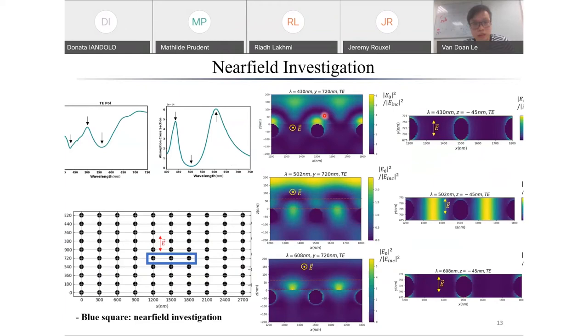So at the first point, at 430 nanometers, the near field is taken at the blue square region here with three nanoparticles. To be clear, at the first wavelength you see the near field distributed around the nanoparticle, indicating localized surface plasmon resonance. So the first dip of absorption is due to the surface plasmon resonance. At the second point here, you can see the field is tangential to the grating surface and mostly on the reflection side, which means that it represents the Rayleigh anomaly.